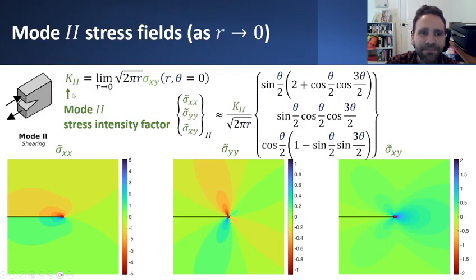That limit defines the mode 2 stress intensity factor, and you can plug it in a similar fashion and notice that all the stresses zoom off to infinity in the local vicinity of the crack tip, but they do so in different ways. Nonetheless, it is still the sigma xy stress that really generates that shearing deformation or shearing separation that leads to propagation of a crack that would extend further off to the right. So along this plane, it's really the shearing stresses that are driving crack growth.